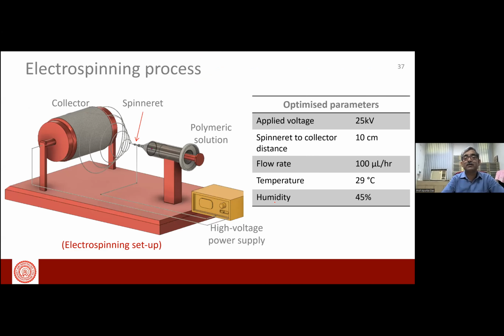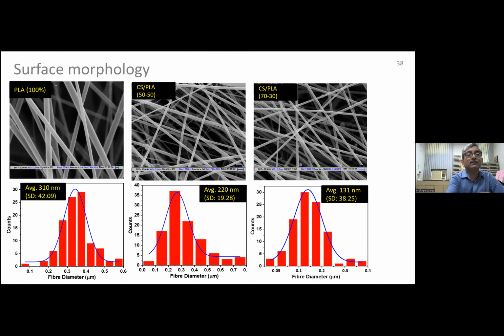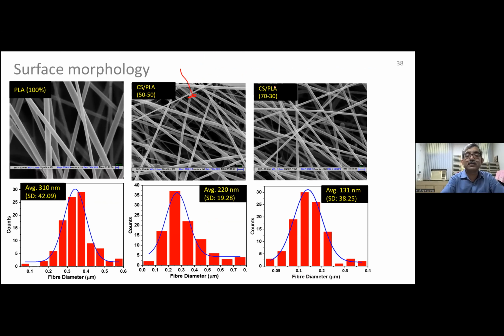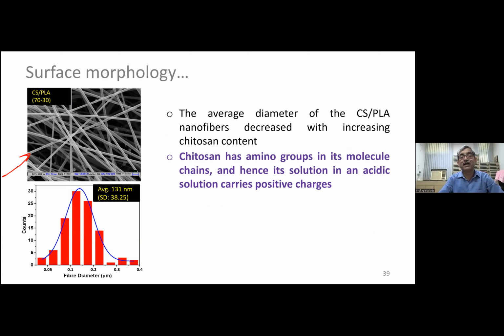What we have observed, as the chitosan content is increasing, the fiber diameter produced is reducing. So 70-30 chitosan and PLA is giving the minimum diameter of 131 nanometer, which we could develop. So we have used this fiber. We have actually developed this electrospun layer on the polyester substrate.